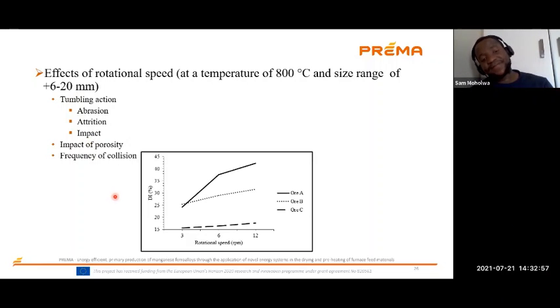Here, as you can see, if you remember from the results, we have OA, which was the most porous, which is why it has the highest DI compared to the other ores, which makes sense. Then the other thing is the frequency at which these particles collide with each other or the walls of the container. In other words, it's the frequency at which this breakage mechanism of impact happens. If you have the rotary kiln rotating at a speed of 3 RPM, the probability of these particles being calcined in the kiln colliding with each other and the walls of the container is very much lower than when you have an RPM of 12. So this is one of the reasons why you have a higher DI at higher rotational speed.